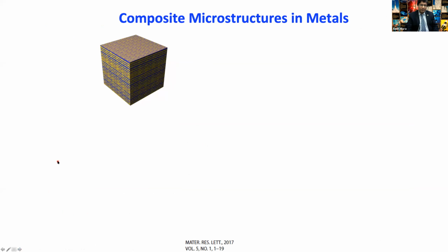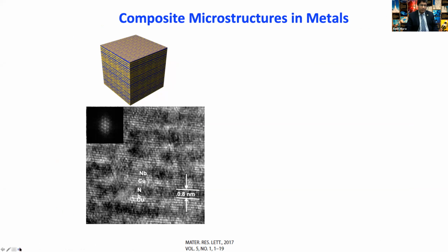So I will give you an example of how you can have a composite microstructure. The previous one was a single phase microstructure, like pure copper. In this case, you can create a layered, nanolaminate type of structure by layering 2 different materials. They could both be metals, or one could be metal and one a non-metal, creating a composite microstructure. So this is an example from copper-niobium. Copper is face-centered cubic. Niobium is body-centered cubic. And you see this superlattice kind of structure formed by physical vapor deposition, where each individual layer can be controlled by deposition. So this is on the order of a nanometer, but we can, by deposition, make it whatever dimension we'd like.